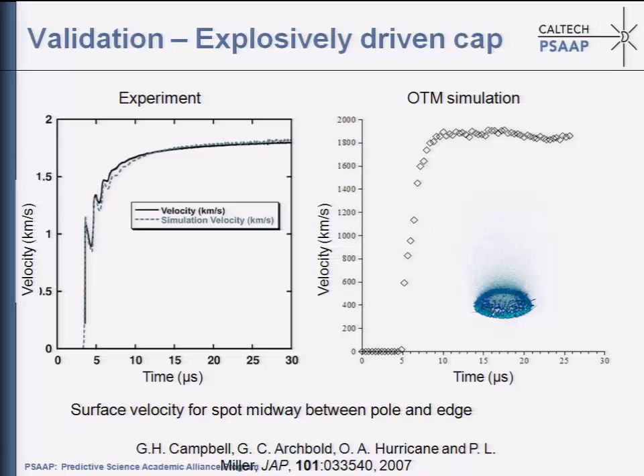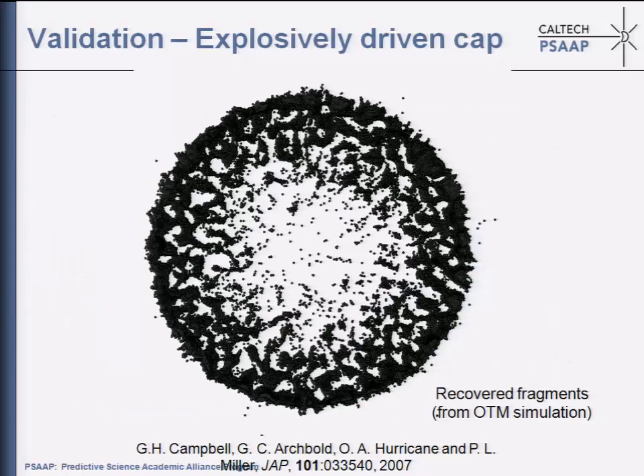Okay, so you now have measurements you can compare against. This is the experiment, the velocity at some point in the shell versus time. This is what you get from the simulation. It's not entirely perfect, but considering that we didn't simulate the drive exactly, I think we are in the ballpark. And these are the fragments recovered from the simulation. At the end of the simulation, we looked for the fragments that are in excess of a certain size and put them back together. So these are the recovered fragments, not from the experiment, but from the simulation.